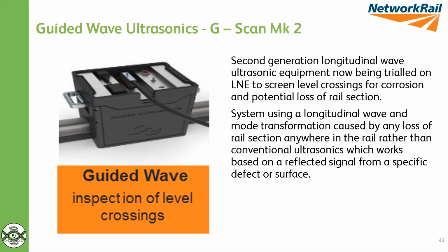So this is currently the next generation, out there now. It's being trialled on LNE to look at level crossings primarily as a screening tool. So it can carry out a non-destructive test without lifting the panels to see if there's any extent of corrosion, predict when they need to perhaps do a more detailed inspection, but also perhaps avoid lifting the panels, finding there's no rail and ending up with a speed restriction or chasing around for a new length of rail to put in in a short period of time. So something to perhaps better target when we need to lift crossings, which crossings are particularly at risk, where we've got some difficulties. So that's just going through some trials at the moment.